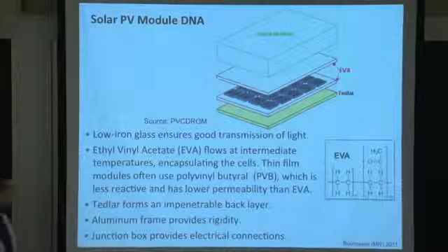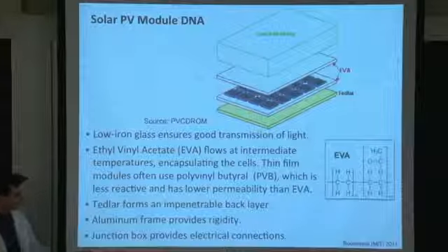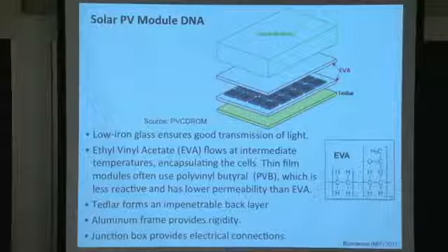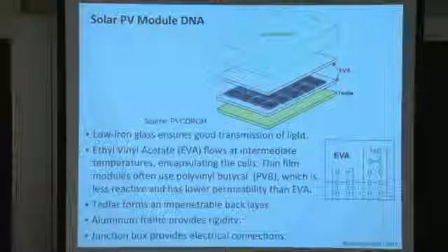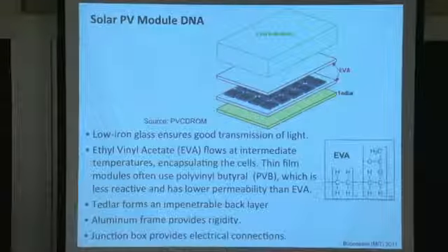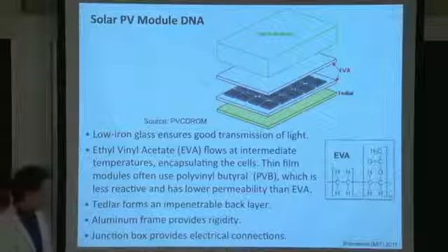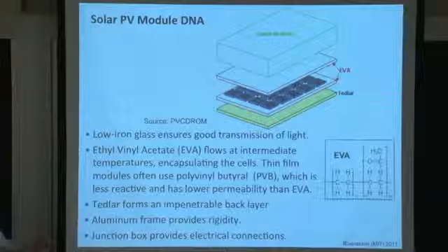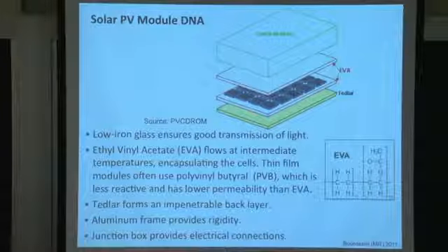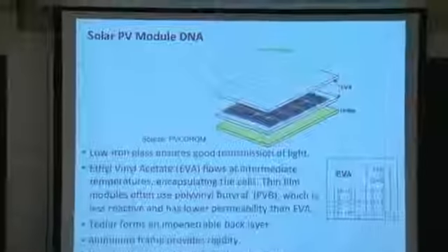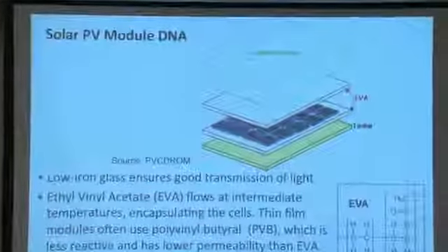They have contact metallization on the front side, which we deposit, say, for example, by screen printing, which you've done in the lab downstairs. And then you string them together using a machine called a tabber stringer to connect one cell to the next, essentially the front of one cell to the back of the next. And they're all lined up like that. And you deposit layers of EVA, which is ethyl vinyl acetate. This is typically the encapsulant material used. It's shown in red right here in this drawing. It's the encapsulant material used for crystalline silicon PV.